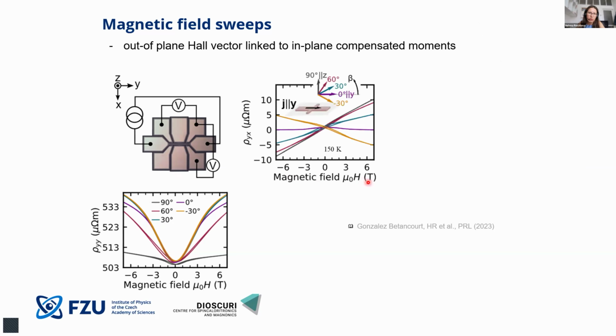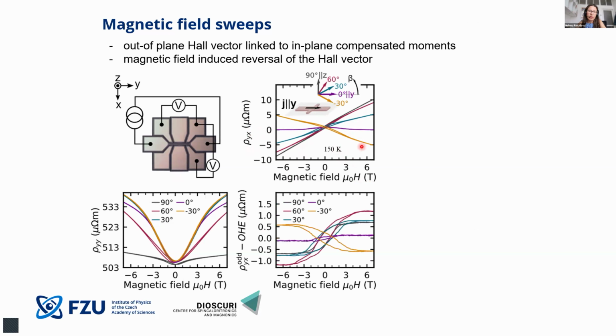And then when we look at the as-measured data on the transversal signal, we see that the signal is dominated by the linear contribution, the ordinary Hall effect, as expected for a semiconductor. However, after subtracting the linear background, simply a straight line, we immediately see that there is some signal left, and this signal has several characteristic features. First, the signal is so-called spontaneous. What I mean is that the signal is present in zero magnetic field, and it has two states.